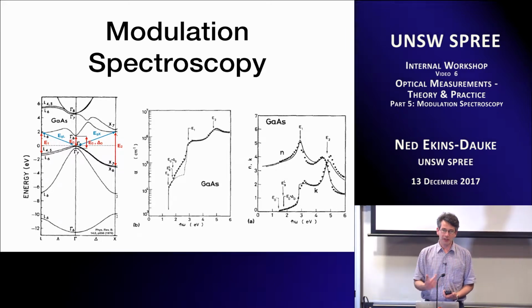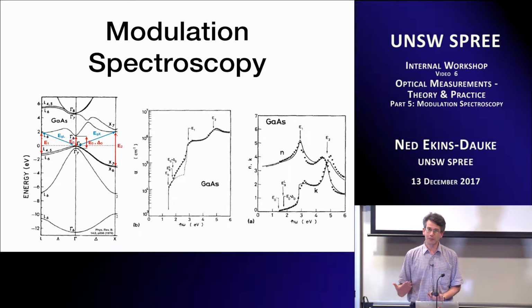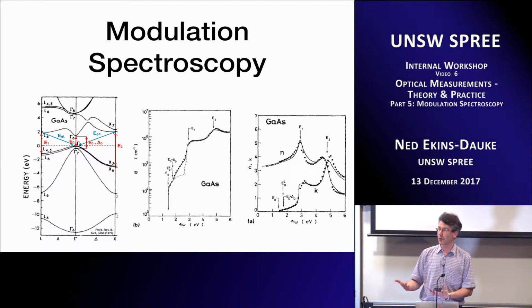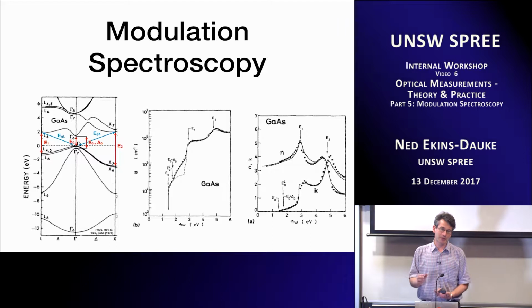I would like to emphasize the last thing Yvonne said, though, because it's important. If you don't care about the underlying physics, you probably will get a better fit to many peculiar materials if you have a completely non-physical but Kramers-Kronig consistent model. So all you're doing is just saying, here's a function that describes N and K, and it's consistent with those Kramers-Kronig transformations.